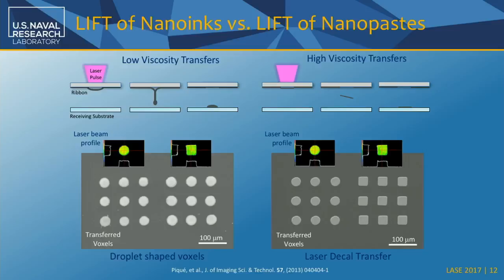Notice that when we transfer the low viscosity ink, the shape of the aperture doesn't play a role. We effectively get a disk on the transfer because, remember, we created a droplet. The way I like to think about this is that we lost information. There was information on the spatial profile distribution of the laser, and when we work with low viscosity inks, we're not able to maintain that. That's what happens with inkjetting, for example, so the shape of the nozzle really doesn't play a role. But when we go to high viscosity, we have what we call a congruent transfer. In those cases, the shape of the laser pulse is maintained and reproduced on the transfer.